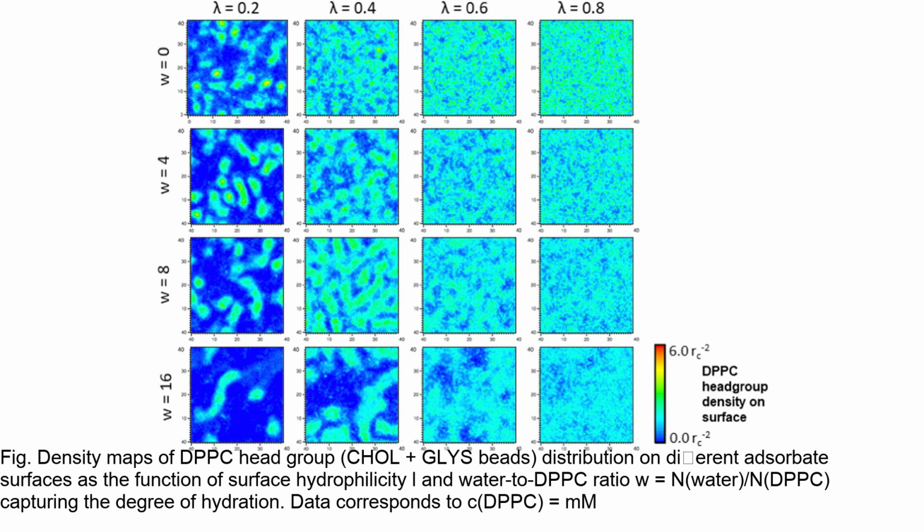The results and conclusions related to Figure 7 indicate that the adsorption of DPPC is influenced by the surface hydrophilicity and water content. Hydrophilic surfaces promote monolayer formation, while hydrophobic surfaces lead to aggregate adsorption. Water acts as a competing adsorbent on hydrophilic surfaces but also promotes aggregate growth and adsorption on hydrophobic surfaces. These findings have implications for understanding and designing lipid-based microemulsion systems and their adsorption properties.